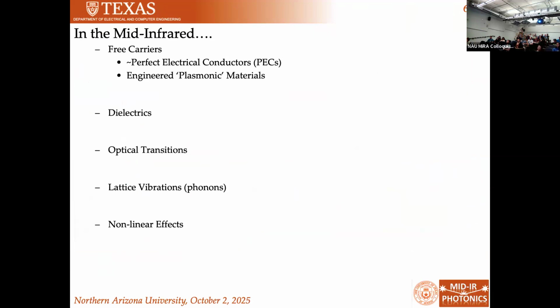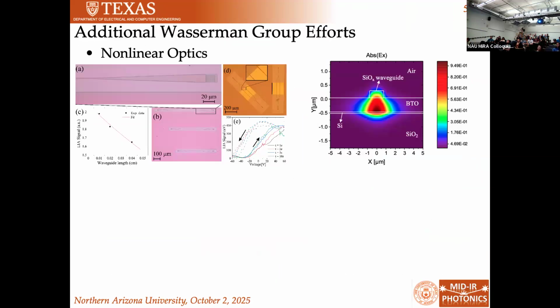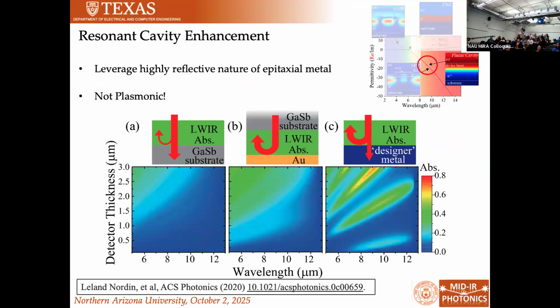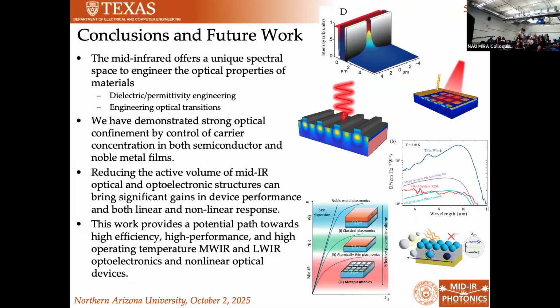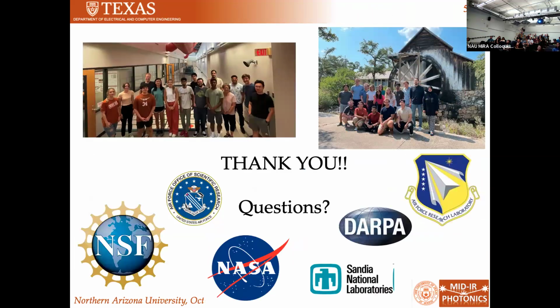Yeah, so it turns out, and thank you for asking this question because it gives me the opportunity to talk a little bit about this, that if you can make your detectors very thin, you can pull the carriers out much faster. They don't have to travel through 8 microns of material to be collected. So we've shown that in our long wave infrared detectors, we can achieve time resolution on the order of a couple hundred picoseconds, which is really fast for a mid-IR detector. It's much faster than you can buy off the shelf.